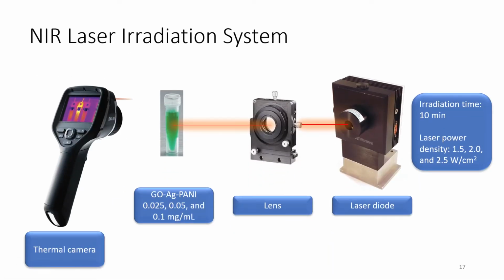To determine the photothermal performance of our nanocomposite, we used a laser diode at the wavelength of 808 nanometers. Irradiation times were 10 minutes in all samples, and laser power density ranging between 1.5 and 2.5 watts per square centimeters. We used a lens to focus the laser beam into the dispersion of our nanocomposite, and for the monitoring of temperature we used a thermal camera.